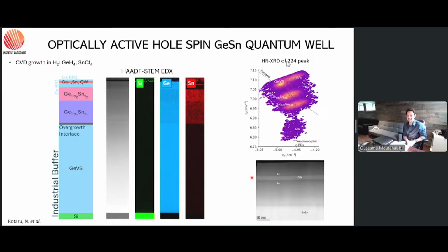You may have some vacancy trapping, charge, and dislocations that can contribute to background doping. We might also have to handle parallel conduction, if there is any, in these devices. So there are so many open questions, and whenever we have any transport measurement, we second guess ourselves: is this exactly the inherent behavior of the device, or is there something else?